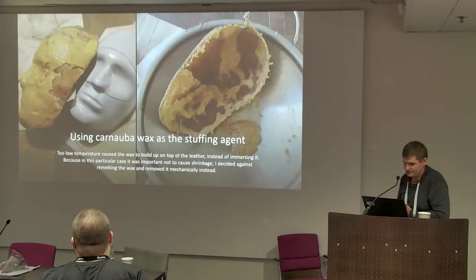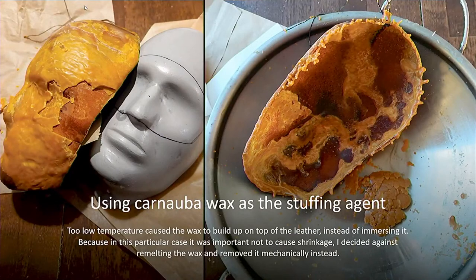With different waxes, you get different results. This is carnauba wax. I had to be really careful when making this piece so it wouldn't shrink too much during the hardening. So I had to have it too cool, and the wax didn't absorb into the material, so you can end up with something like this. Because I didn't want to risk any further shrinkage, I mechanically removed the wax. So that's one problem of using carnauba wax.